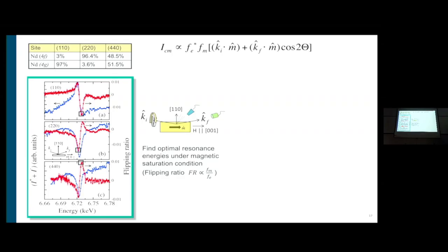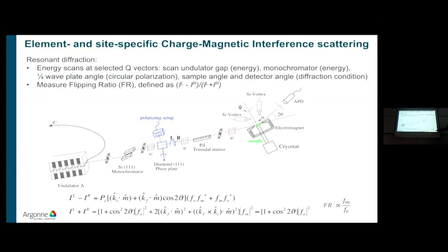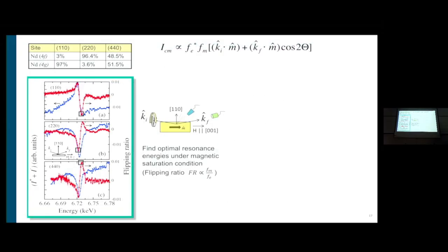quantity. So what's shown here is in blue is the resonance charge. So we are adding the 2 helicities back here. We are adding the 2 helicities, and remember the other terms cancel. We just get the charge scattering. So the blue is the sum of the helicities. So that's your resonance as you go through the neodymium L, I think 2 edge. For different Bragg conditions. So in this condition, one neodymium side contributes, here is the other, and here is both.